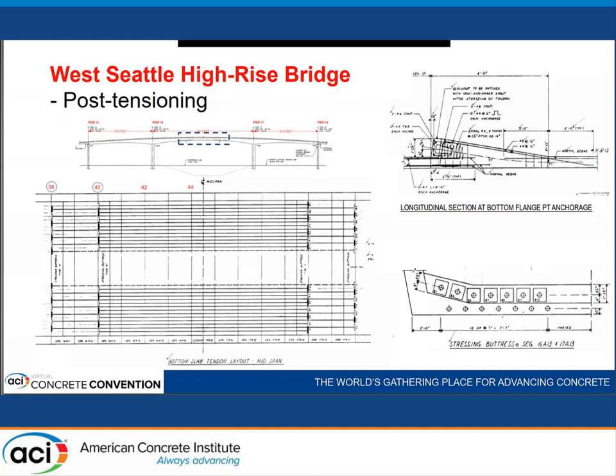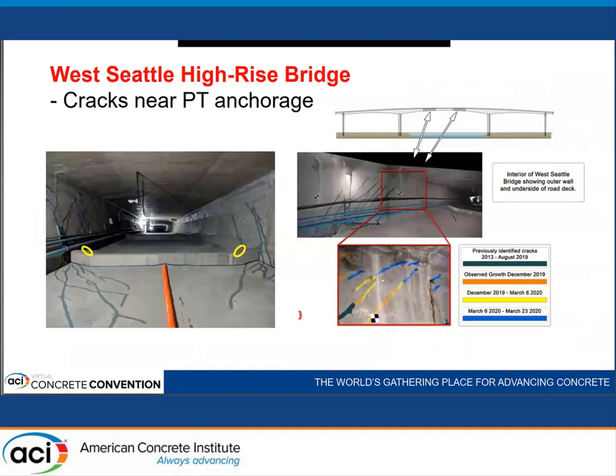The blister comes up from the flange and sticks up, and then an end view of that buttress where it's anchored, just to get an idea. So a lot of the cracks actually are emanating in the area around these anchorage points. So there's a change in stress condition at that location that has contributed, in addition to the believed long-term creep, to contribute to growth of these cracks.